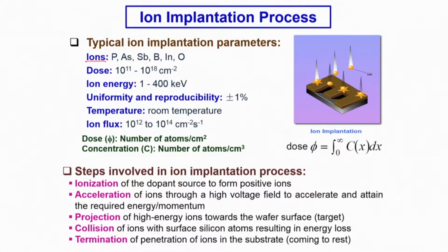So what are the elements or species that we want to implant? If it's a semiconductor, then you would naturally think of elements which belong to group 3 or group 2 if you want to create a p-type, or group 5 or 6 elements if you want to make an n-type semiconducting region. So accordingly you'll choose elements from phosphorus, arsenic, antimony, indium, or boron, or various other typical